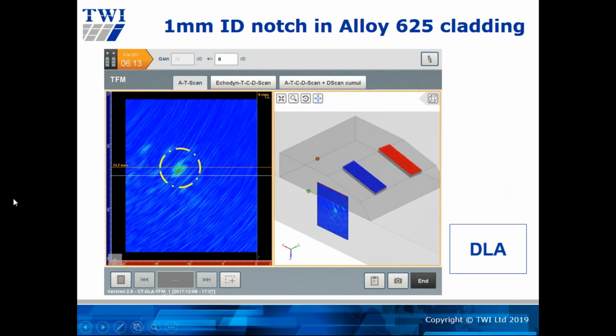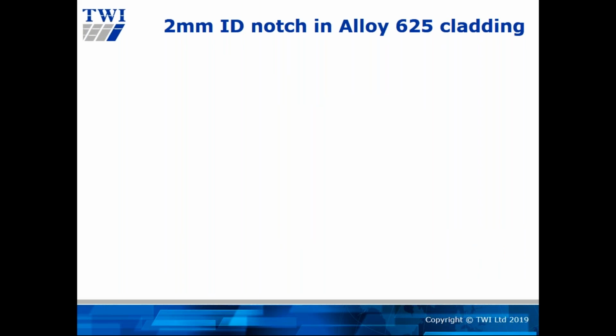If you look at the third technique, the DLA technique, what you see is a much cleaner image. Here the signal to noise is much better, you have much reduced noise, and you can also see the signal here. It is actually possible to do some form of through-wall sizing. But in our procedures for this kind of inspection, we don't specify sizing because that is not well conditioned because of the skewing aspects of the beam, because we cannot be sure of the sizing, and that's an area that is a piece of ongoing work that we are resolving.